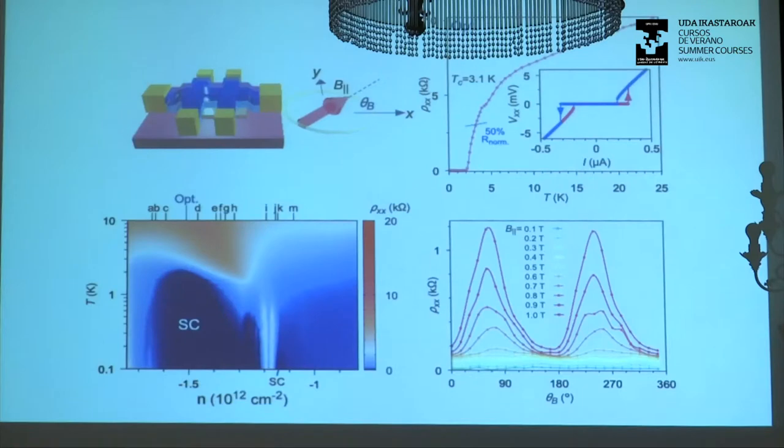So we take a device, a magic angle twisted bilayer graphene, and we have four probe measurements, so we measure resistance. This is a device with a pretty high TC, 3.1 Kelvin, at 50% of the normal state resistance. This is the complete dome versus density, in log scale, so that you can see some features more pronounced. And if you now measure the resistivity as a function of in-plane magnetic field magnitude and direction,